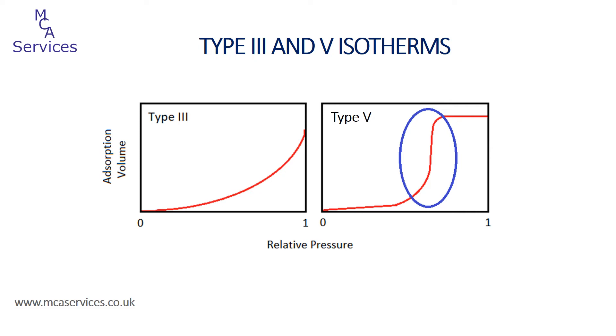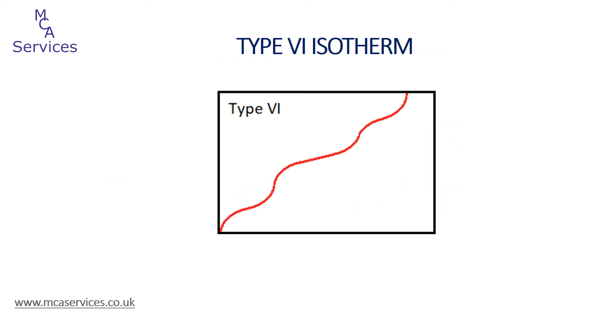These isotherms have been observed with water adsorption experimentation. The type 6 isotherm is really quite rarely observed. The adsorption isotherm consists of a number of step adsorption increments with increase in relative pressure. These steps are generally taken as being due to successive adsorption layers on the surface of a uniform non-porous sample — for example, argon or methane adsorption on graphite. Both of these are near-spherical non-polar molecules adsorbing to a very regular, uniform surface.